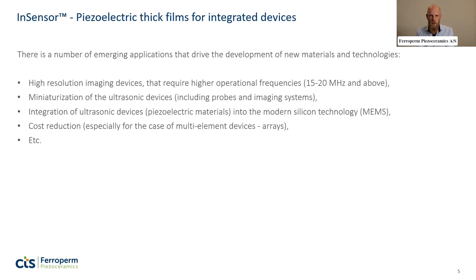Piezoelectric thick film. The drivers behind developing piezoelectric thick film is basically to open up the application space possible where you would like some kind of a piezoelectric actuation or sensing. Some of the applications that we have in focus here is high-resolution imaging devices that require high frequencies. And by high frequencies, we're talking about 10 megahertz and above. Here it says 15 to 20, but we are normally operating in the range of 10 to 50 megahertz for these kinds of devices. And for conventional bulk ceramic technology, this can be a challenge to machine parts that enable those frequencies.